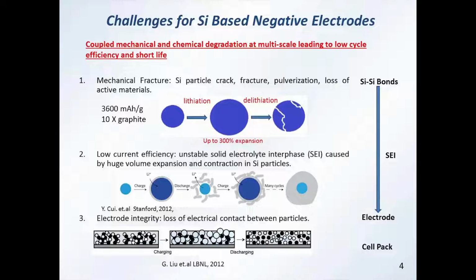So during this huge volume change, the surface stability of the silicon particle will become very poor, which causes a lot of electrolyte reduction, such as irreversible reactions, forming the solid-electrolyte interphase, or SEI. And I will introduce SEI in the following pages.